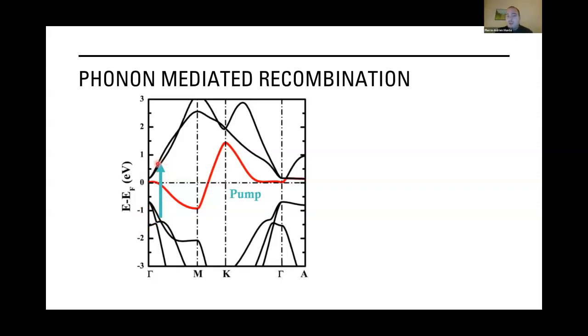And when electrons are going to relax through electron-phonon coupling, they are going to accumulate at this M point, which is the lower part of this band that is straddling the Fermi level. On the other hand, the hole will be predominantly accumulating at the gamma point.